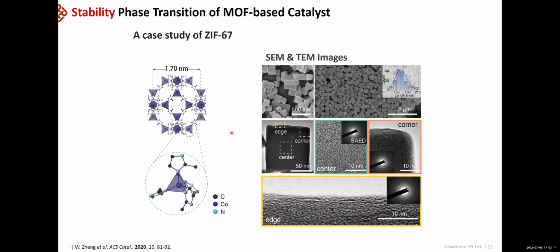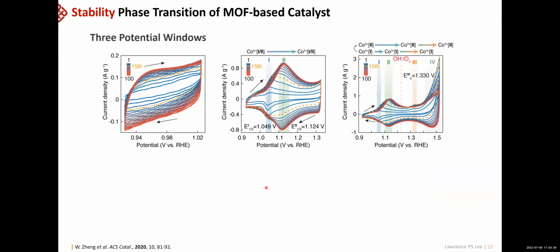And the reason why we chose it is not only because it has only one metal, but they are known to be stable in electrolytes, and it's very easy to grow onto many different surfaces, including our electrode surfaces. So we first study their cyclic voltammetric stability. So we chose three different potential windows, from up to 1.1, about 1 volt, to 1.3 and 1.5 volt, and we cycle them about 100 times.